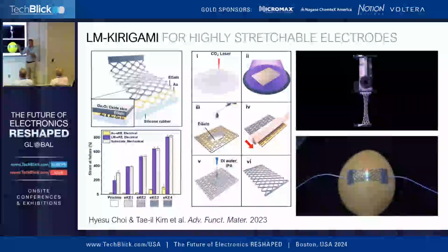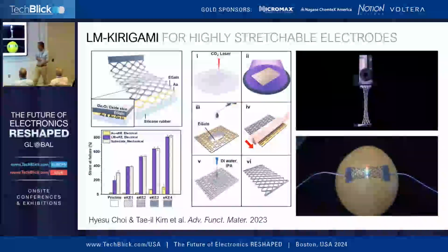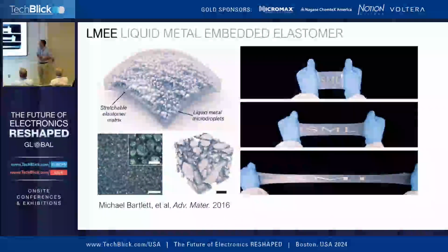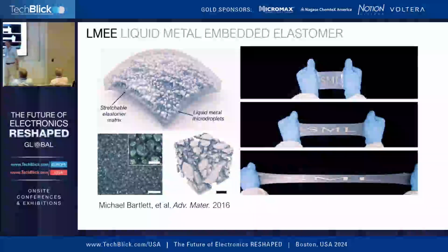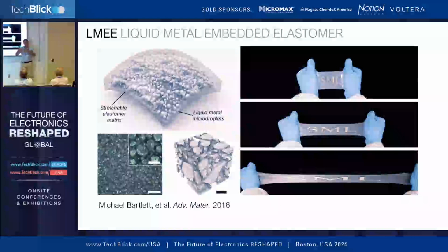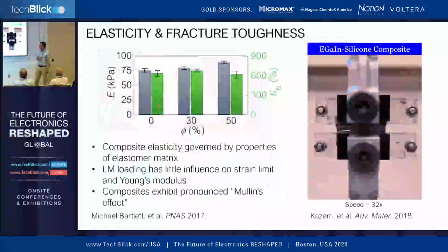So moving to an architecture that is more compatible with printed circuitry, we shifted from having just thin films of liquid metal to having dispersions of micro and nanoscale droplets of liquid metal within a soft rubbery substrate. Typically we use silicone rubber. This also works with urethanes, fluoroelastomers, polyacrylates, pretty much any soft polymer out there. If you have a high enough density of these liquid metal droplets, and again, these are microscopic, somewhere between 100 nanometers to about 10 microns in diameter, we can actually form percolating networks of these droplets and get conductive pathways.